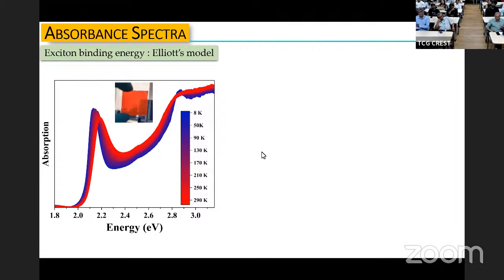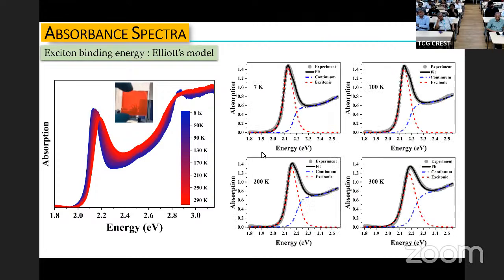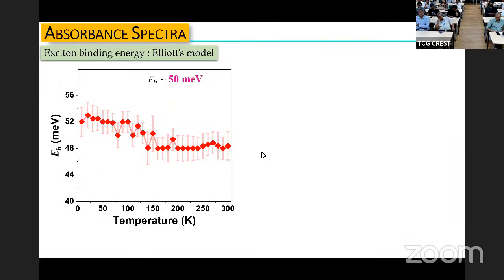It turns out that how you extract the excitonic binding energy, which technique you use, changes it a lot. In fact, photoluminescence and other techniques have been used. We believe absorption is the best way, so we are using absorption to extract the excitonic binding energy. And these are the fits of how we do it. There's a free absorption, and this is the excitonic absorption feature, and that gives you the excitonic binding energy.